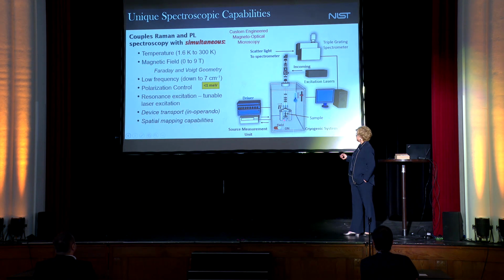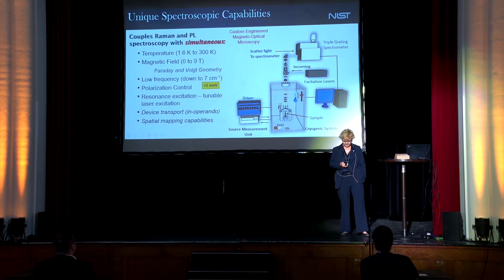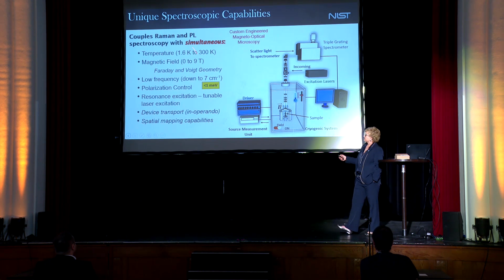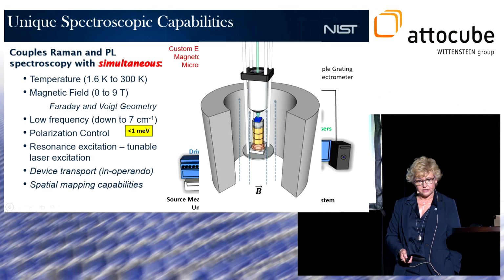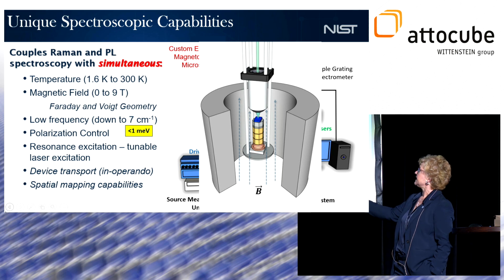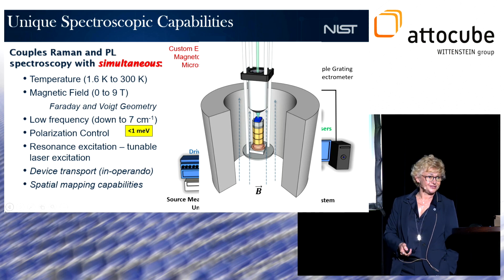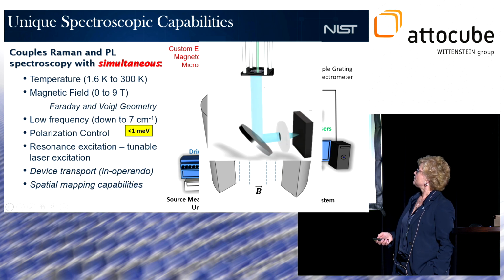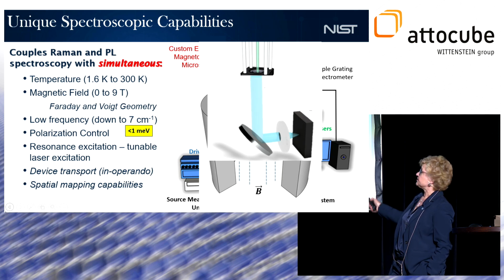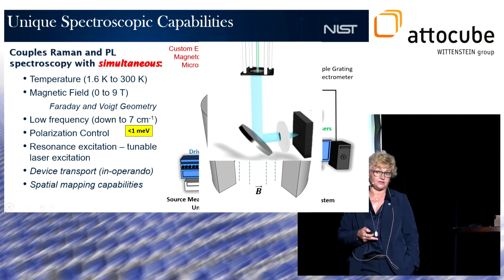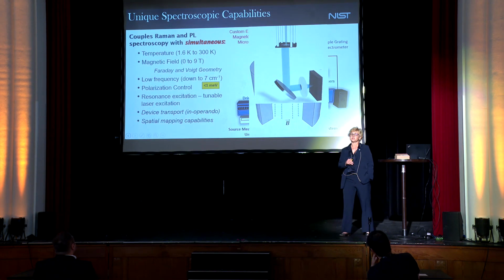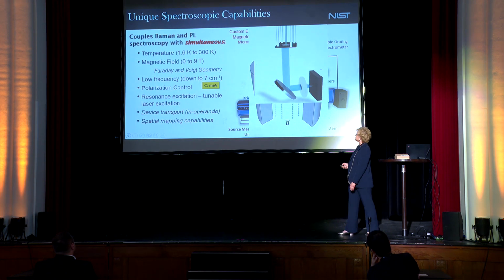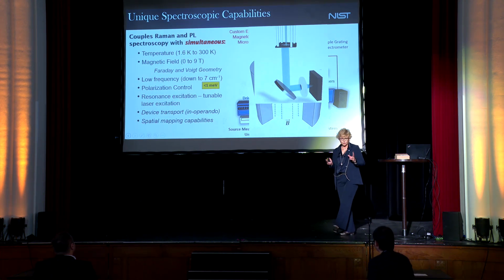We have from attocube, of course, the magneto-cryostat. In our case, we go from 1.6 Kelvin up, and we have two different geometries. We have the Faraday geometry, where our sample is sitting in the XY plane on top of all kinds of positioners and rotators. And then we have another version, which is called Voigt. In this case, we stand up the sample so that it's parallel to the magnetic field. This is really important in trying to assign magnons.